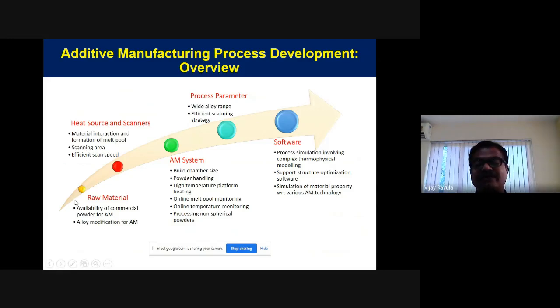Our roadmap towards that is that we need to have raw material, which means the availability of powders for additive manufacturing. And because it's a non-equilibrium process, the microstructural development is totally different. The properties we get from conventional manufacturing, like casting and then forging, will be totally different from the properties we achieve by additive manufacturing. So that means we have to have different alloying elements, different systems for the same kind of material.